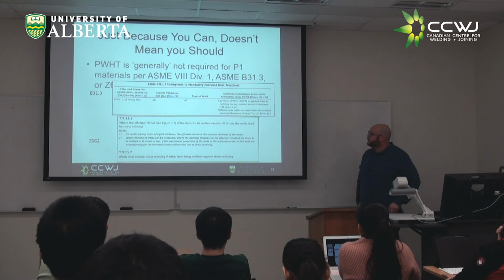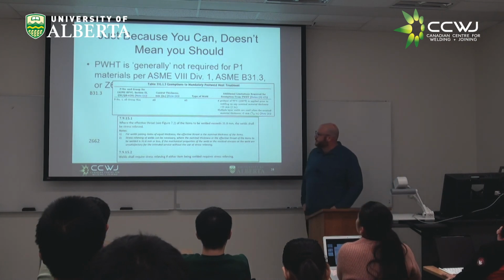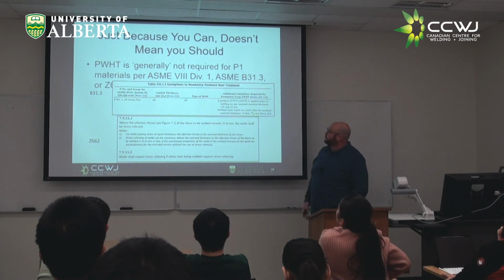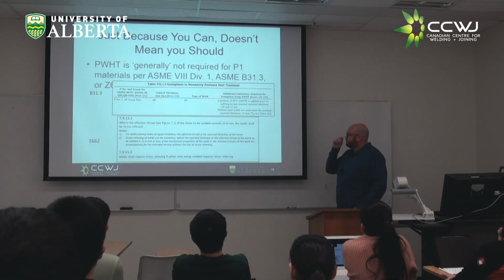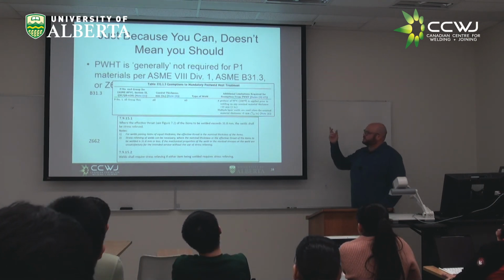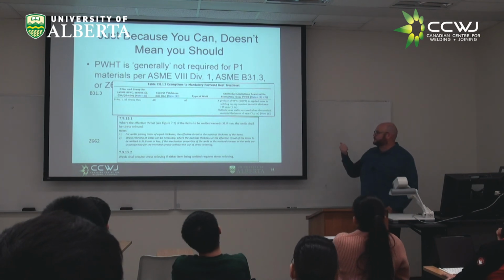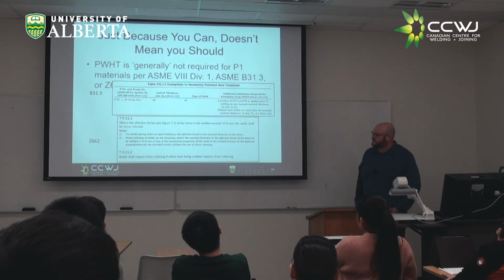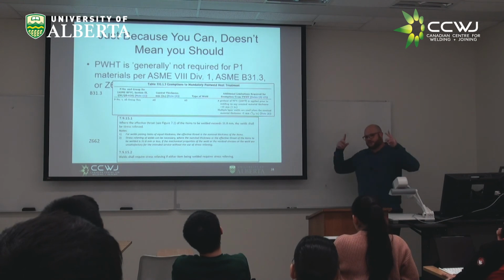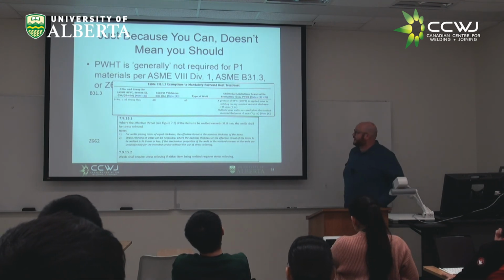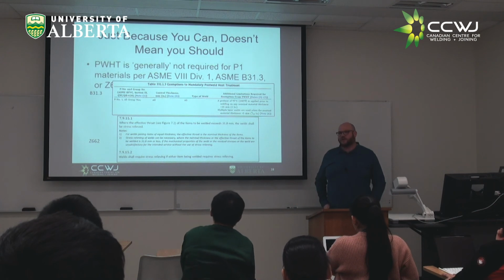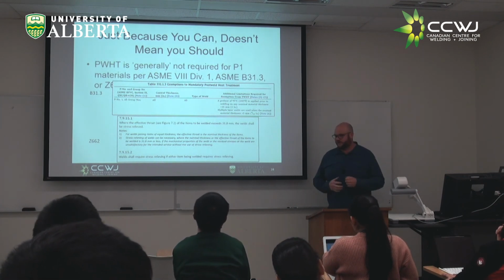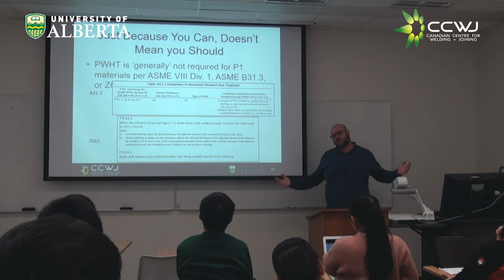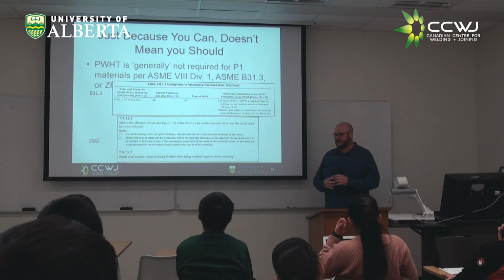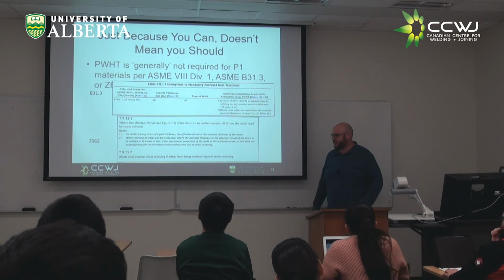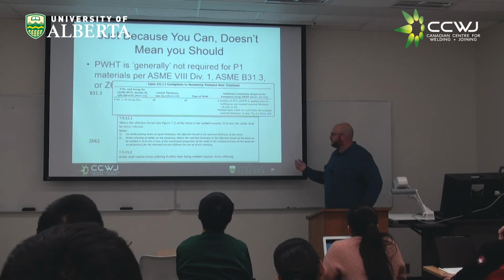Awesome, good. Sorry that these keep on blowing up and covering off the text. But basically, one example of this is post-weld heat treatment. So post-weld heat treatment is generally not required for ASME 8 Div 1, B31.3, or Z662. And the reason why generally is in quotation marks is because the ASME codes actually require mandatory post-weld heat treatment for everything, and then they go through and list a whole bunch of exemptions that basically cover off about 90% of the applications. So it's there, but it's not there.